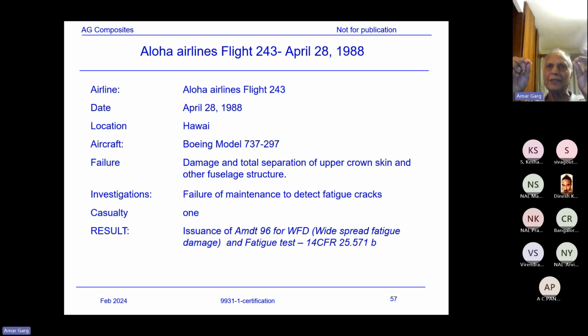During maintenance, they did not detect some fatigue cracks which were propagating. And the cracks kept on accumulating, kept on propagating further and further, and caused a fatigue failure. And that is why later on the widespread fatigue damage (WFD) rule came into the picture, which I'll talk about later on. And that is how Amendment 96 for widespread fatigue damage was issued.